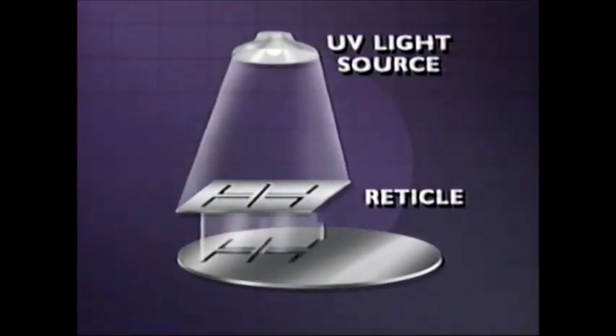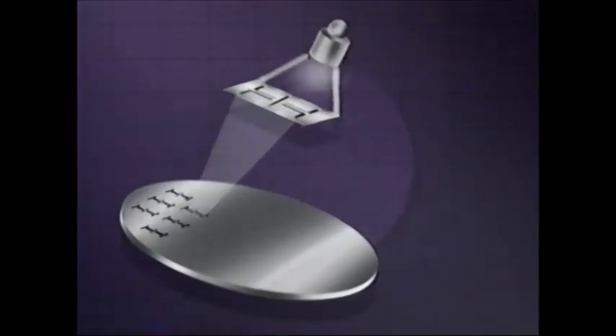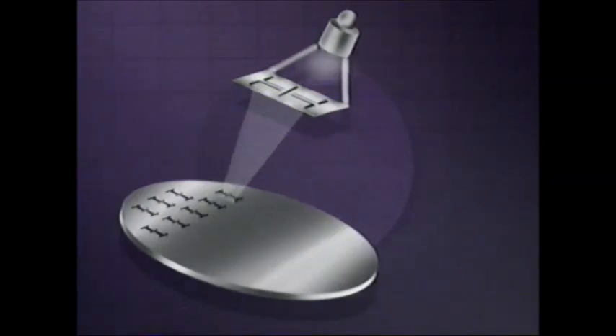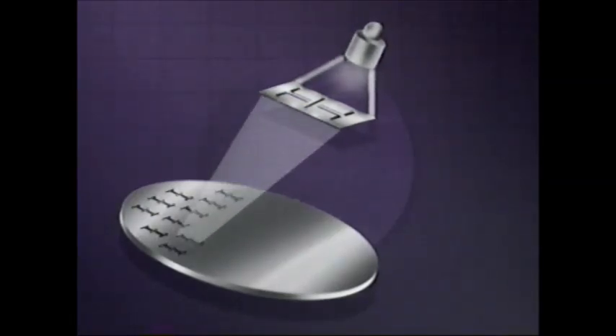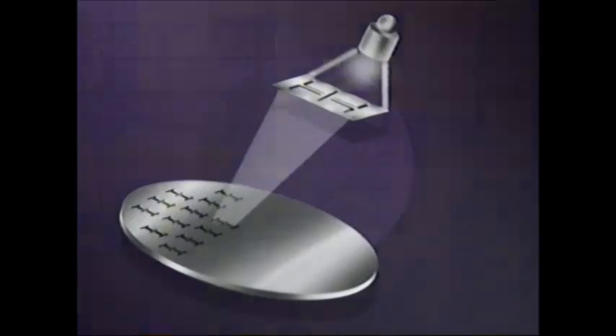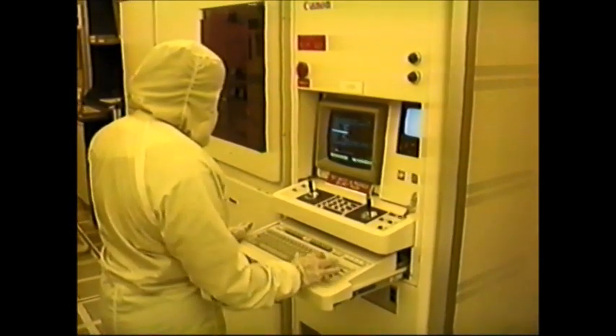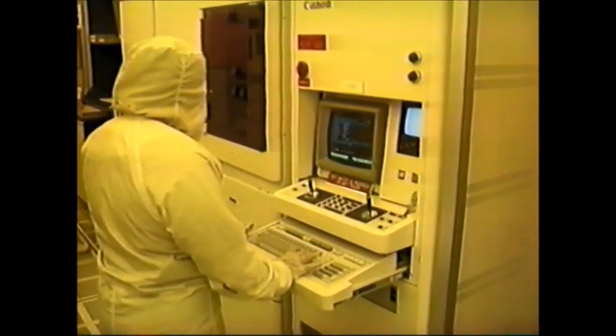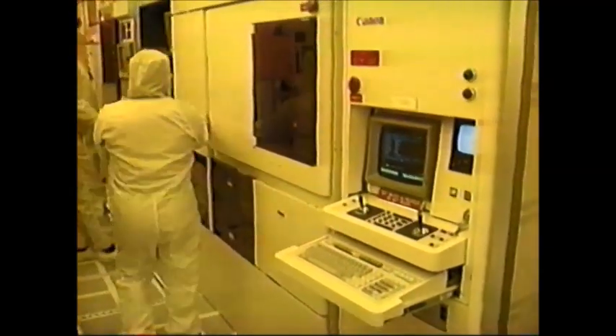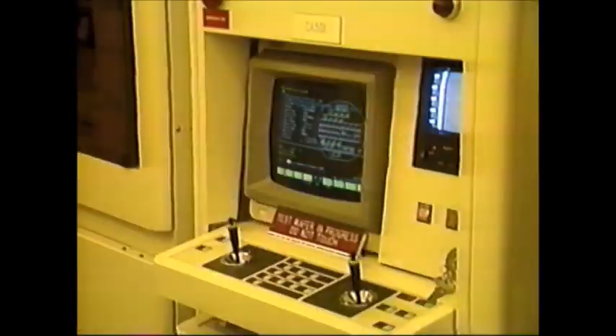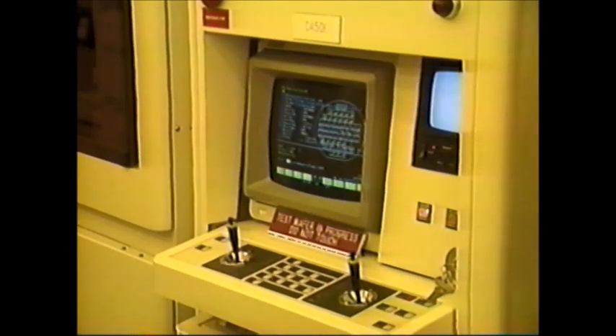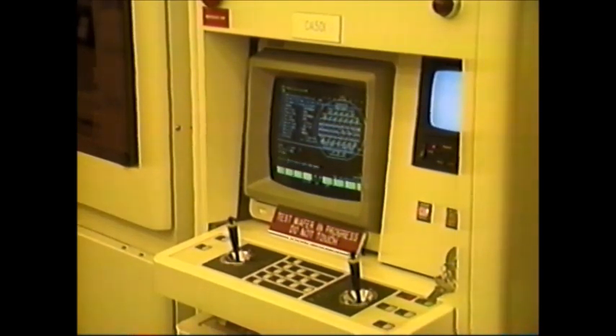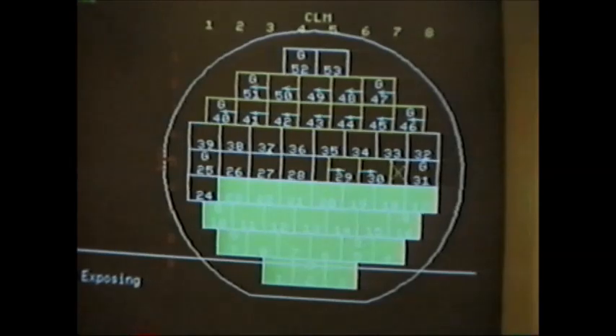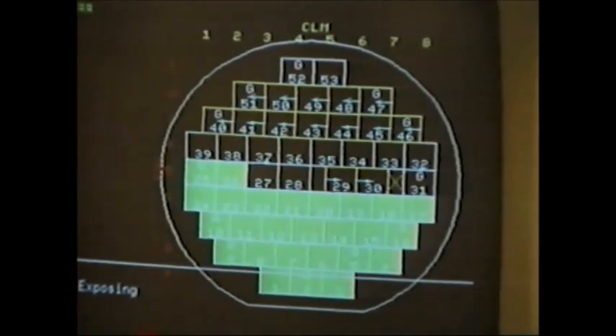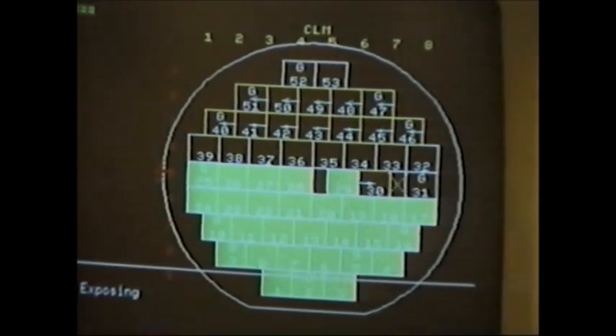Once the wafer has been coated with photoresist and the resist has been baked to harden, it is exposed to ultraviolet light through the photoreticle. Because of the extreme detail required, the reticle is usually made to expose only small areas of the wafer surface, one area at a time. To cover the entire usable surface of the wafer, the reticle is stepped over the wafer using precise computer positioning controlled by a device called a stepper. The wafers are aligned by a computer which scans special patterns which have been printed on the reticle and etched on the wafer. This step method of exposure is capable of geometries as small as 0.12 microns.